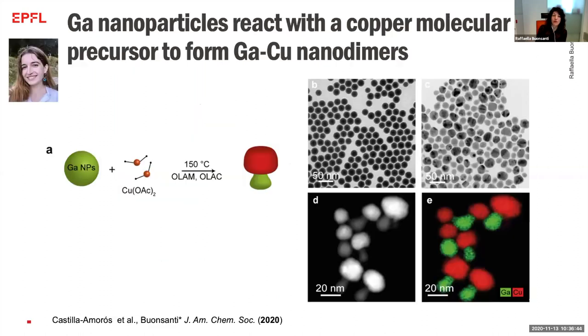So Laia, my student, tried this experiment. She reacted the gallium nanoparticles with a copper molecular precursor, and we obtained these nanodimers again. Now, nanodimers make sense in the case of silver copper, because based on the bulk phase diagram, silver and copper are immiscible. Copper and gallium should alloy. So at this point, what we understood is that gallium, which is a liquid metal, is different and not the same as the noble metals.